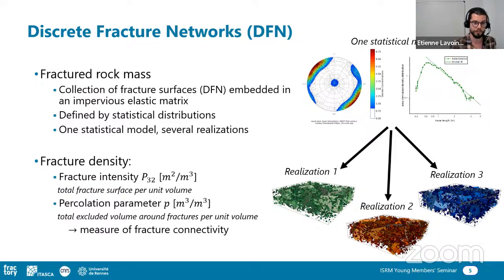So a lot of physical concepts rely on the fractures themselves. And these fracture surfaces are defined by statistical distributions. And you have one statistical model, but you need several realizations. So for example, you go in the field, you take some data, so you have orientation data, you have size data, and then you create a conceptual model, a mathematical model, where you define different fracture sets, different statistical distributions for the orientation, but also the size distribution.